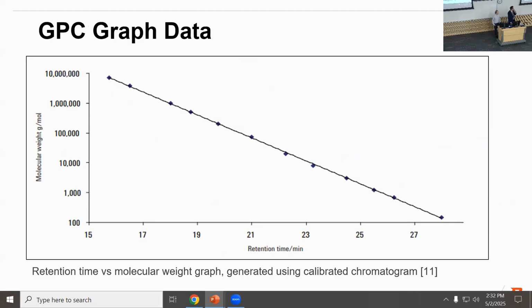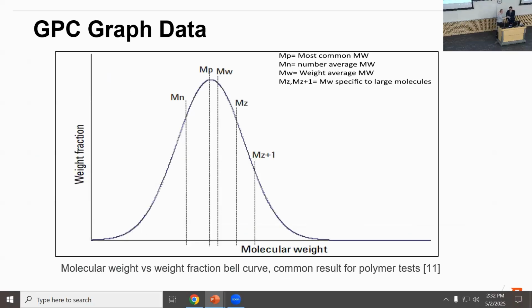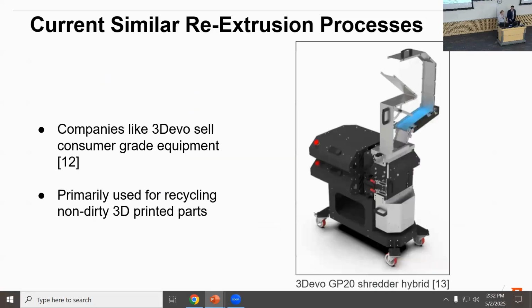At the end of this, you'll typically find a calibrated sensor that's able to detect when these pass through. And this figure is a very idealized version. It's usually not going to be this linear, but you should see a negative correlation between retention time and molecular weight, with the highest retention times being the smallest molecular weights of the sample. And so basically you would expect a normal distribution similar to this, which can tell you how many of what size molecular weight is a part of your plastic.